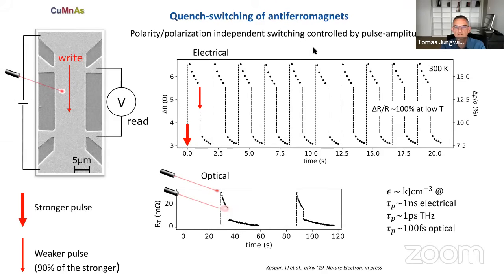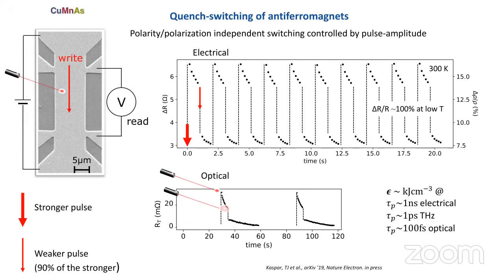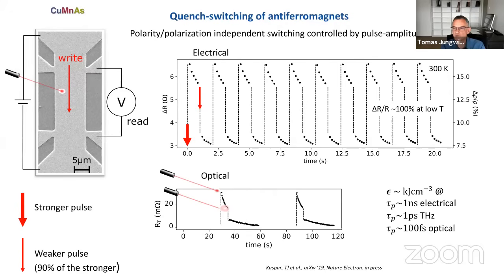So this is the electrical experiment, and the optical experiment is exactly the same in spirit. You deliver the optical pulse, where we did either a train of pulses to see how it depends on the number of optical pulses, or we could do a single femtosecond laser pulse, deliver it, and then wait for a macroscopic time, seconds, then deliver the next pulse, which has a lower intensity. And we can do this by just slightly defocusing the same laser.